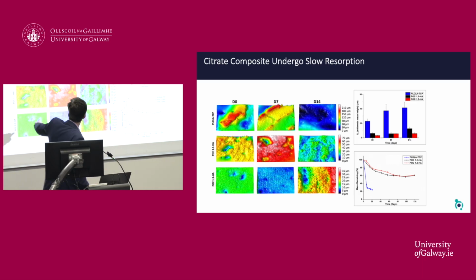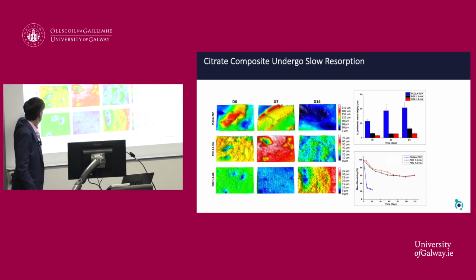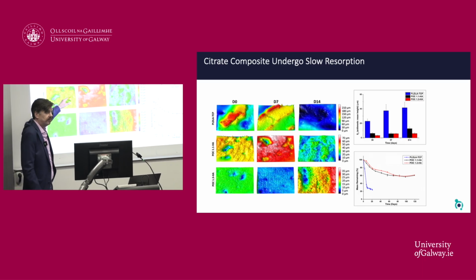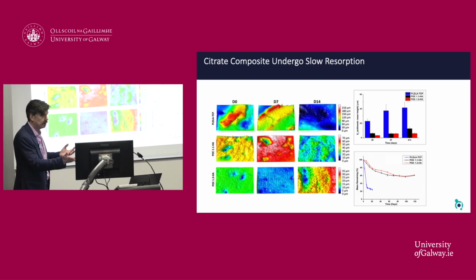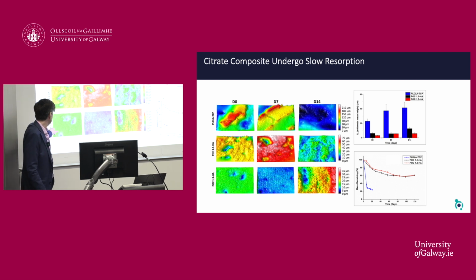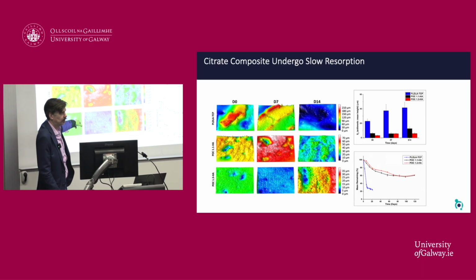One was, we call POC 1.1. This has a 1-to-1 ratio of the polymer to the ceramic. And another was POC 1:1.3. So it had slightly more ceramic. We looked at these two formulations. And I refer to these as POC 1.1 and 1.3 going forward. Okay? One is slightly more ceramic.